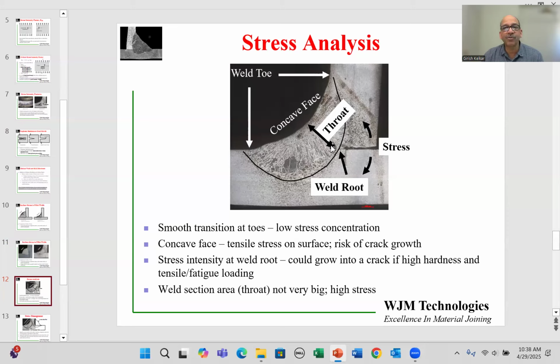We also have a fairly narrow throat over here, and we also have a feature at the weld root, which effectively acts like a crack, even though the weld itself does not have a crack. But there is a crack-like tip right at the edge of the weld at the weld root. And now when we are applying a tensile stress on this weld, based on the fact that the weld is on one side only, that is also going to introduce some kind of a torque into the weld, which will tend to open up that weld root if the stress is high enough. So these are the things we have to change. We need to have a different profile. We need to increase the size of the throat, and we see if we can eliminate this unwelded portion itself.